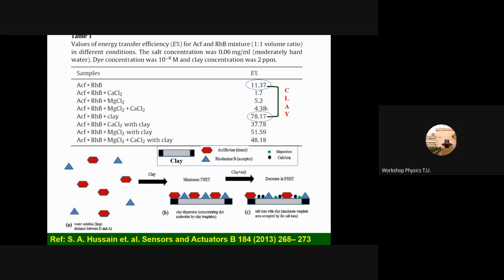Then what we did, we put clay in the system. Then you can see that instead of 11, in case of energy transfer between only the dyes, in presence of clay, it reaches 78%. Then we put this magnesium, calcium or both. Then you can see that the energy transfer decreases from 78 to 37%, or 78 to 51% or 48%, and the difference is very good so that you can distinguish.